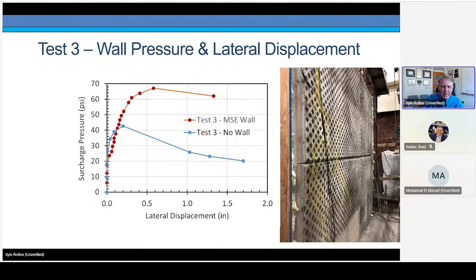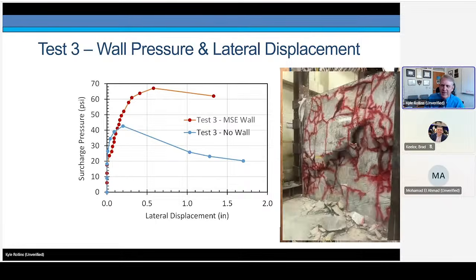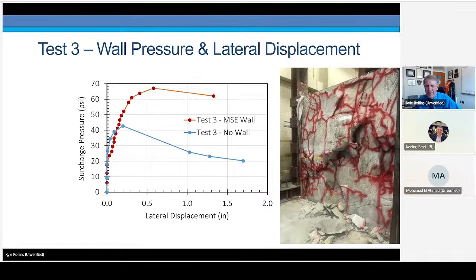Then the other case with the MSE wall, we can apply again another 20-something PSI surcharge pressure before we get failure. So this is a photo of the failure of the free face wall. You can see it's ready to go. These blocks are coming off in chunks. The additional capacity that we're getting from the strips is on the order of 20-something PSI. Again, contrasting the behavior, we have a brittle behavior with no reinforcements and a fairly ductile behavior with reinforcements in place.